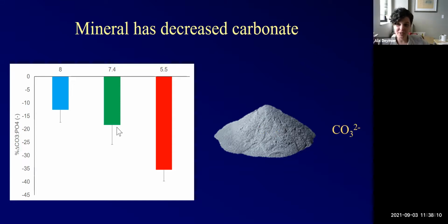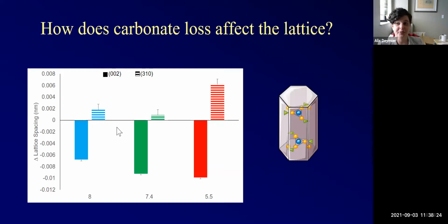But now we have the advantage that we're just looking at a powder of nano mineral, essentially, which gives us the opportunity to much more easily do other material science analyses. And the one we were most pumped to do, which is my favorite technique, is X-ray diffraction. So in X-ray diffraction, we can get a change in lattice spacing as a function of the pH. Down here in the solid bars, this represents the 002 lattice spacing.